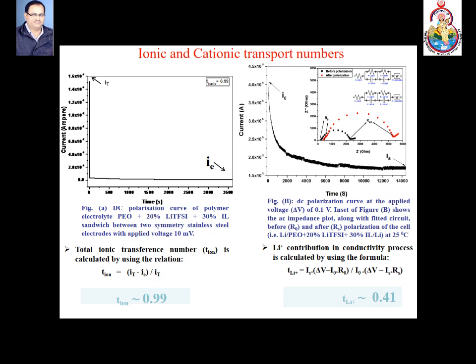Ionic transference number is one of the key parameters for characterizing the Ionogel electrolytes. The electrolytes which are used in lithium batteries should be perfect ionic conductors and electronic conductivity should be very low. Here it can be seen that the transference number is about 0.99, indicating that 99% of the conductivity is contributed by the ions. One of the important parameters for electrolytes is their lithium cationic transport number. In this case, using the combined AC-DC technique, the lithium cationic transport number is about 0.41, indicating that 41% of conductivity is contributed by lithium ions.